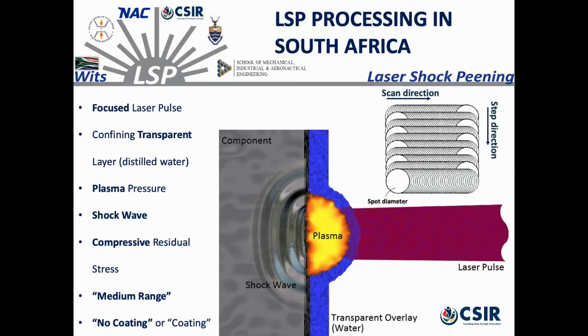So as Prof. Sano and other colleagues showed, there are different ways to do laser shock peening. The way we typically do it in South Africa is we use a medium range commercial laser. And for this specific type of application, we work with no coating, so we have no additional protection on the surface. In terms of confining medium, for this specific work, we work with distilled water, but in some other works, we actually work with